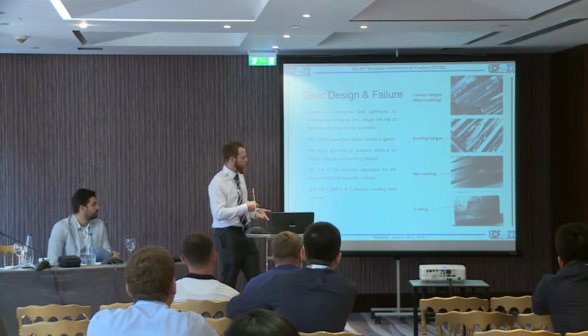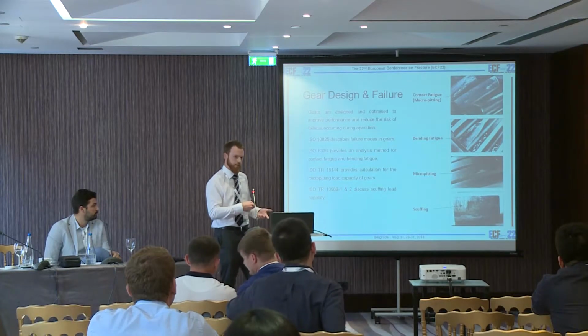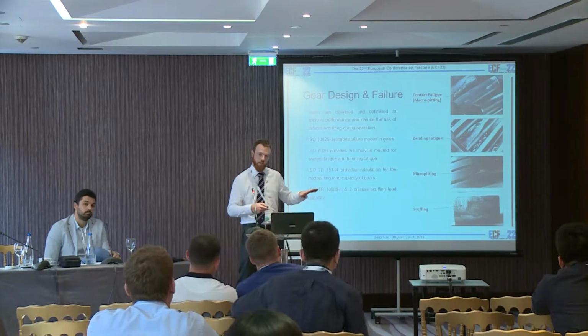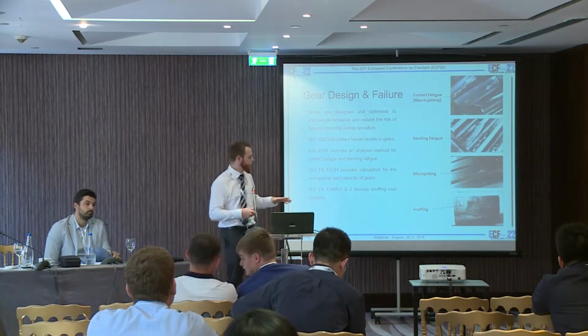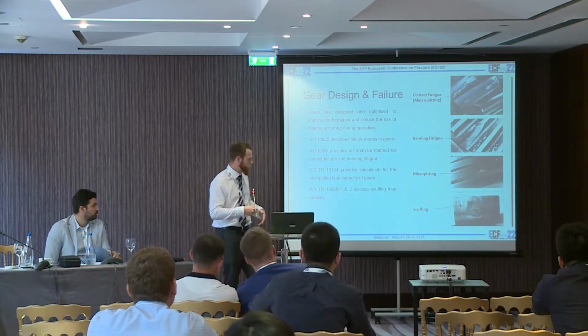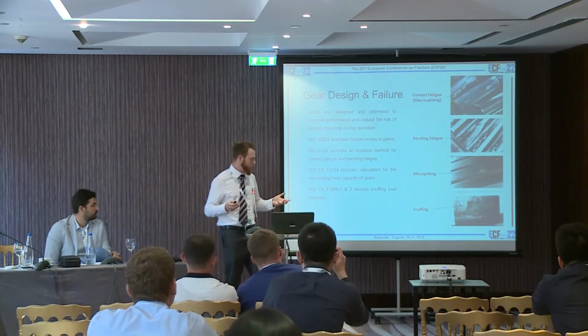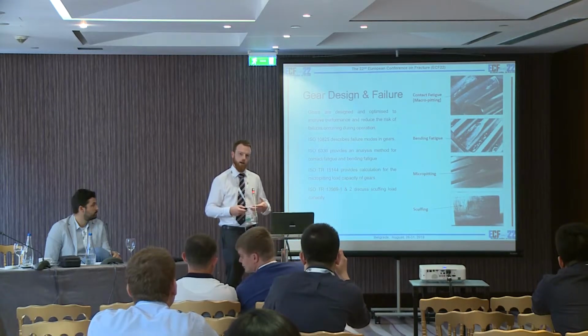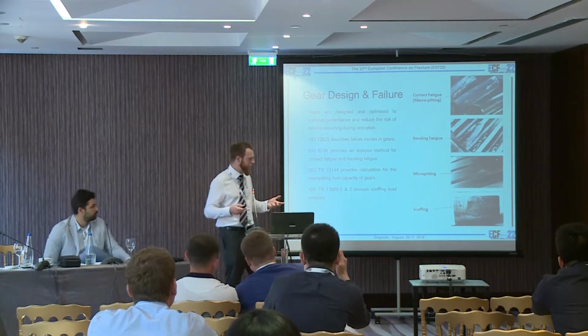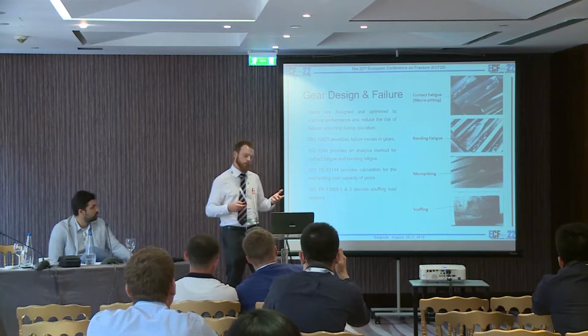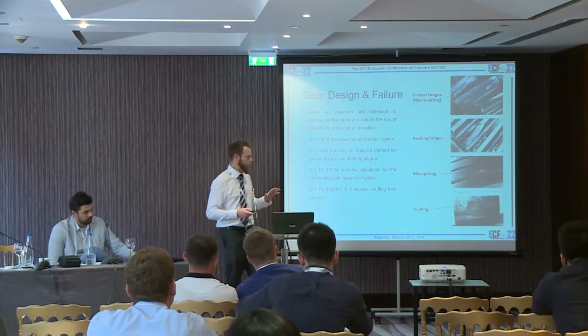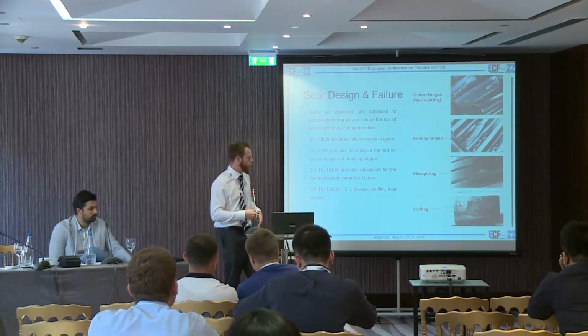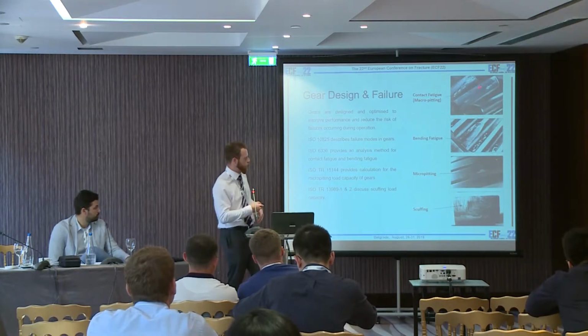But essentially here we have root-initiated cracks growing through the teeth, and we end up with detachment of the gear teeth. We have micropitting, which, if you believe most people, is a fatigue-based failure. Sometimes there's grey staining. We have very shallow surface-initiated cracks, and that's actually a failure that can arrest or lead into further failure modes, typically contact fatigue.